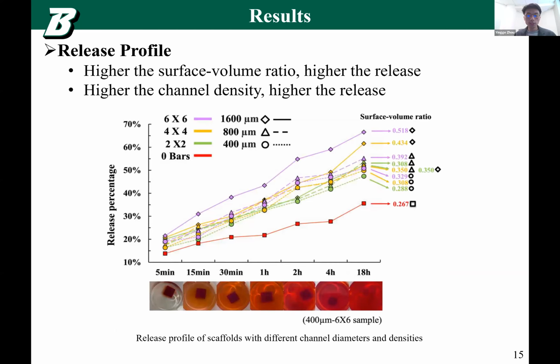And then we try to see if we can control the material release from the hydrogel to the culture medium, or from the culture medium to the hydrogel, because now we have channels, right? So what does it look like if the hydrogel has no channels, and the dye in the hydrogel is going to release into the medium? How fast is it going to be? With no channels, the release rate is pretty low, only about 30% in 18 hours. But with channels, it's pretty high. And the highest is 6x6 channels and the 1600 micron channels. So the larger the channels, the more channels, the faster the release, which is reasonable, right? And this lower one is the 2x2 and 400, as you can see. So this is the drug release. We want to see if we can control the drug or biological release profile.